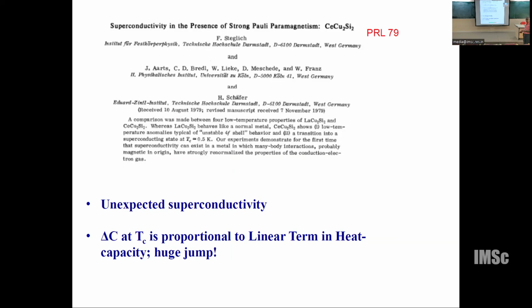I mean, for the benefit of students, the jump you expect at the superconducting transition should be proportional to the electronic coefficient of simple metals, as I just mentioned. In these materials, as I told you, it is three orders of magnitude larger. The jump also scales with that. Therefore, superconductivity comes from exactly the same electrons which are responsible for the heavy fermion behavior. Is it clear?